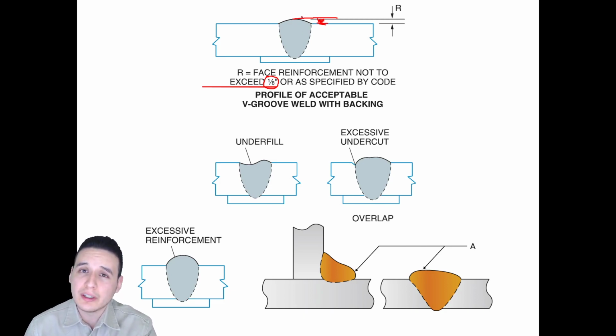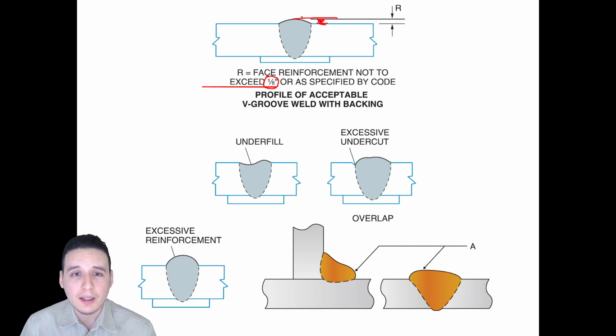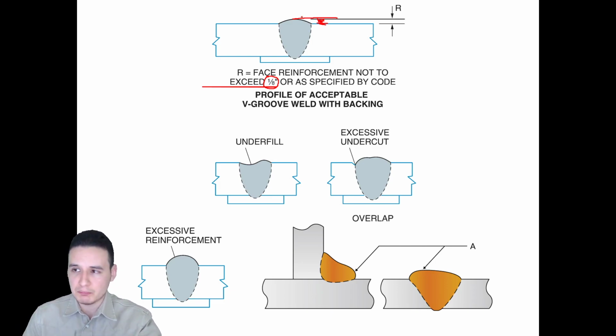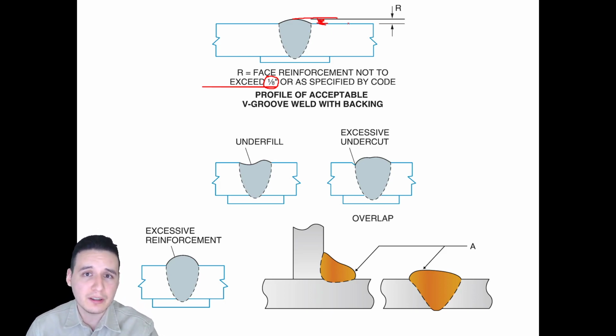If your cap is over 1/8 of an inch, then you're going against code. You're going to fail whatever test you're testing for when you are going out there and getting a job. And of course, I'll be taking off points for that if you're over that 1/8. So keep your cap over 0, meaning it has to be higher than the base metal, but it can't be over 1/8. So that's a little bit of a tricky situation. You have to make sure you're not going too slow as you're doing that cap. An easy way in which you could measure whether you are over 1/8 or not is by simply using a 6010 rod. Remember the 6010 rod that you use there at San Jac, that's a 1/8 rod. And so you could use that to measure whether you're over or not.